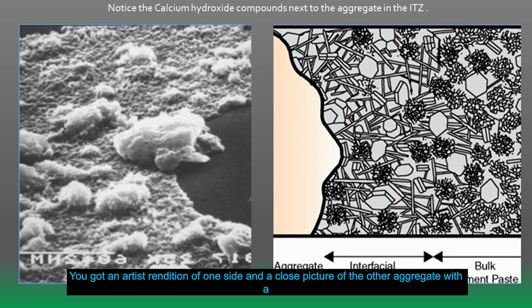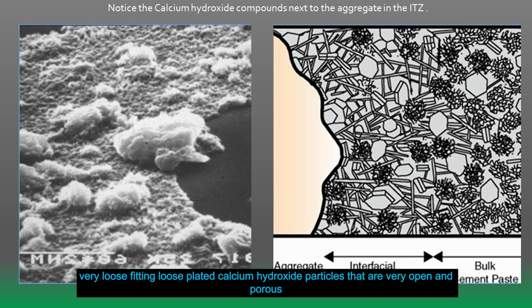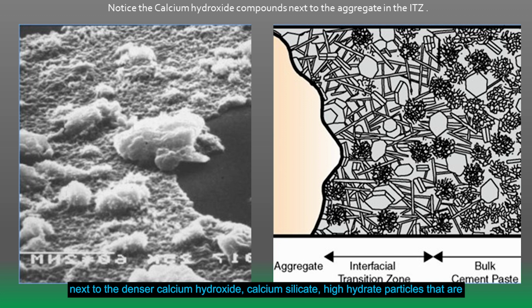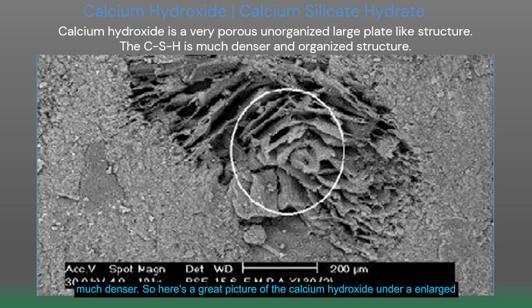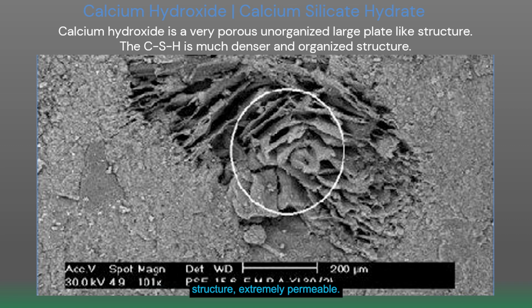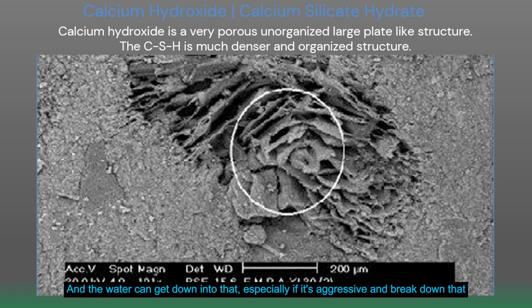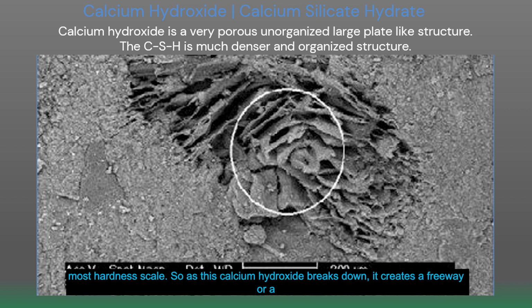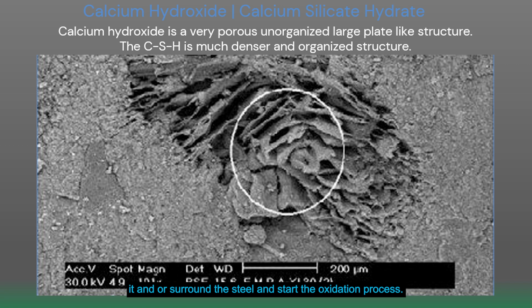Here's an even closer picture. You've got an artist's rendition on one side and a close picture on the other of aggregate with very loose, loose-plated calcium hydroxide particles that are very open and porous next to the calcium silicate hydrate particles that are much denser. Here's a great picture of calcium hydroxide under an enlarged photograph, and right next to it you have your calcium silicate hydrate. Now the calcium hydroxide, you can see, is a very large, loose, plate-like, disorganized structure, extremely permeable, and the water can get down into that, especially if it's aggressive, and break down that soluble compound. And right around that you see the very hard, dense structure of a 7 on the Mohs hardness scale. So as this calcium hydroxide breaks down, it creates a freeway or a capillary system for aggressive waters to get into the cement to break down the rest of it and/or surround the steel and start the oxidation process.